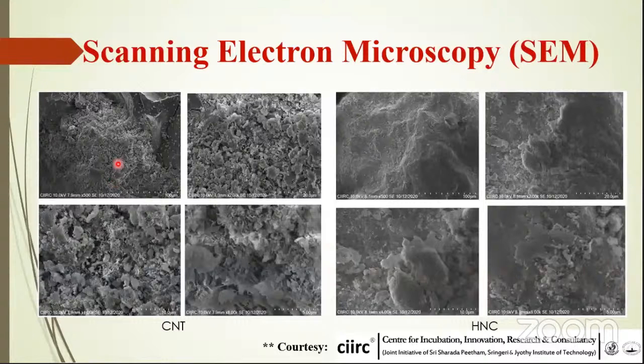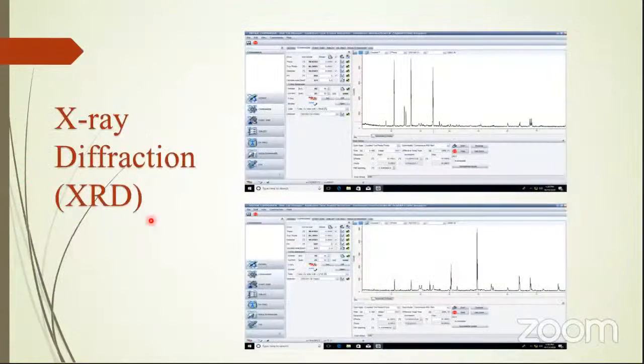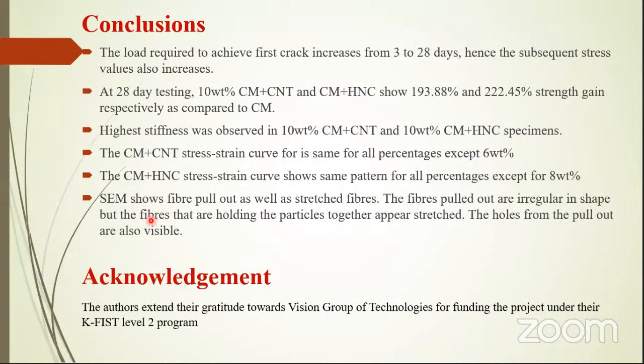Fiber pullout is not exactly clearly visible, but you can see the very, very small holes that are visible. Those are indications of fiber pullout, where the fibers have disembedded from the matrix. And there are some fibers or particles that appear stretched here. So that is available, and so far that is what the study has concluded.